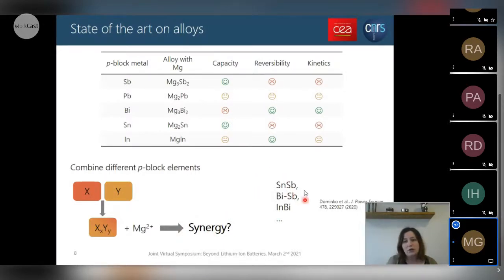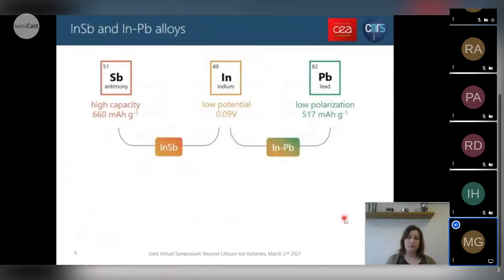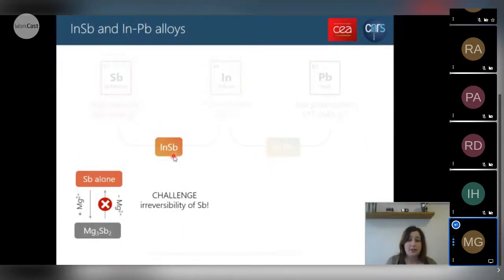In the literature, alloys such as tin antimony, bismuth antimony, or indium bismuth have been investigated. And in our case, in our group, we've looked at two new alloys, which are first the combination of antimony, which presents a high theoretical capacity, with indium, which presents a very low potential. So we combine them in the InSb intermetallic compound. And we also looked at the combination of indium with lead, which presents a very low polarization and an interesting capacity also. So we looked at the InPb solid solution. We will first take a look at the InSb intermetallic compound.